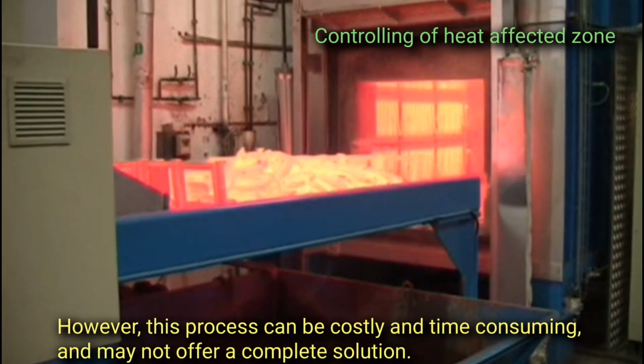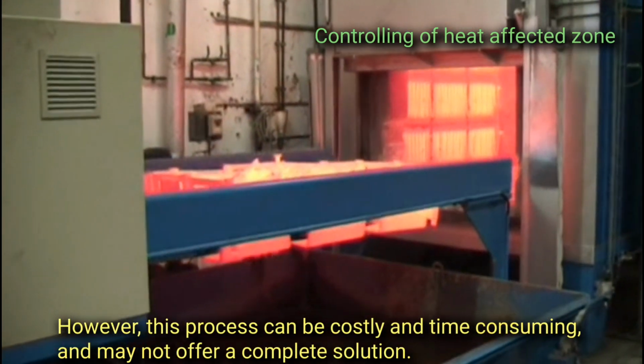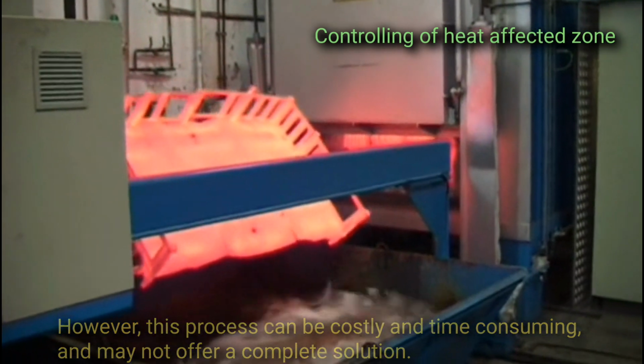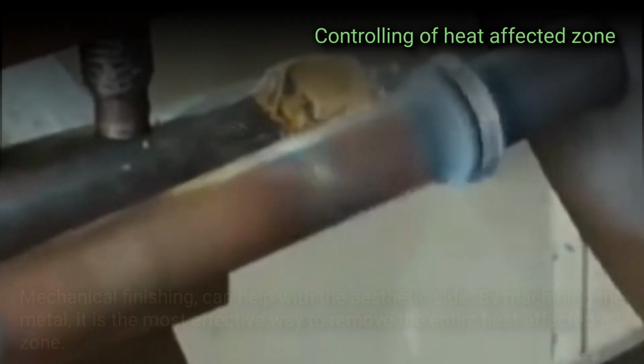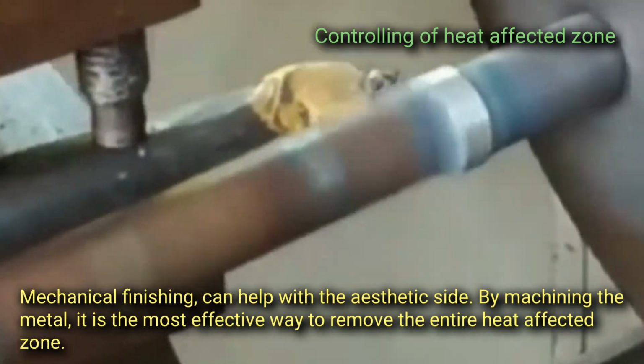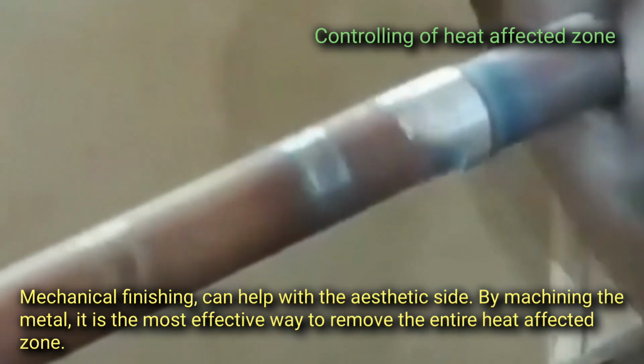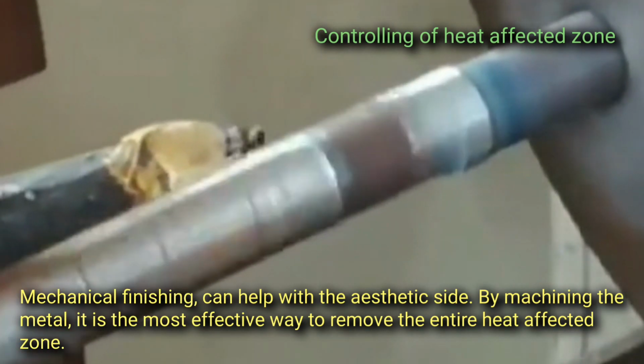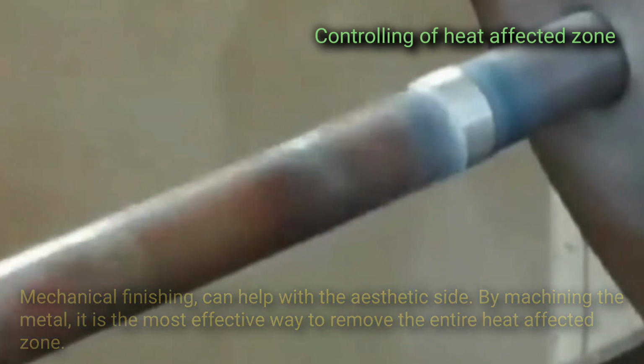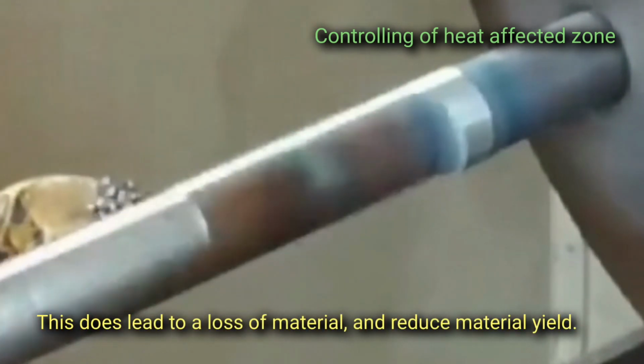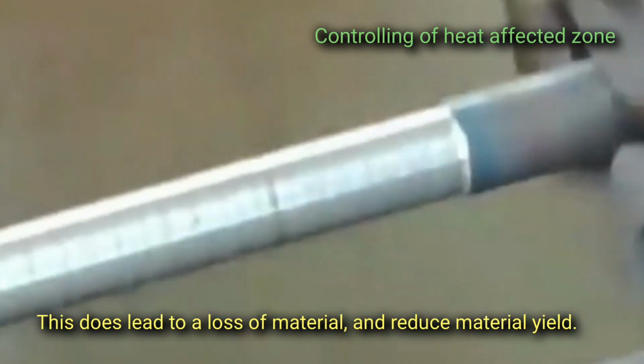However, this process can be costly and time-consuming and may not offer a complete solution. Whether you are cutting or welding metal, the key is speed. Shorter exposure to heat leaves a lesser heat-affected zone. Mechanical finishing can help with the aesthetic side. Machining the metal is the most effective way to remove the entire heat-affected zone. This does lead to a loss of material and reduced material yield.